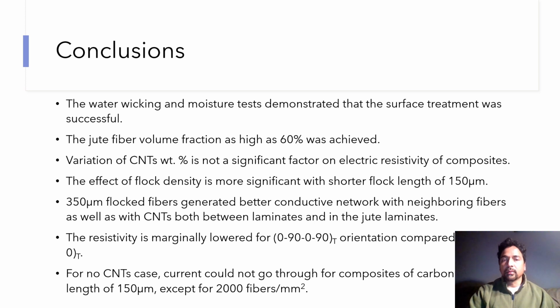And 350 micron carbon fiber composites generated a better conductive network with the neighboring fibers as well as with the CNTs, both between the laminates as well as within the laminates. And resistivity was marginally lower for 0/90 orientation compared to 0/0 orientation. In the case of no CNT, the current could not pass through composites of carbon fibers of 150 micron length, however, the current is able to pass through even for a small flock density of 500 for the composites of 350 micron long carbon fibers.